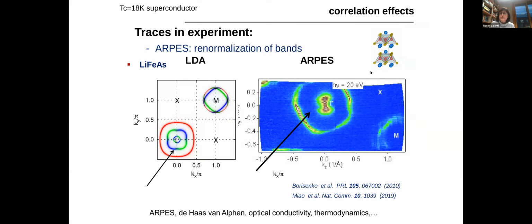I will first concentrate on lithium iron arsenide. This system, we had yesterday a very nice talk about recent ARPES measurements on this material. It's a nice test bed material to investigate these correlation effects, because the system doesn't show a structural phase transition, doesn't show a magnetic phase transition, and doesn't show nematicity. Basically, it's a system in the tetragonal phase that goes superconducting at 18 Kelvin.